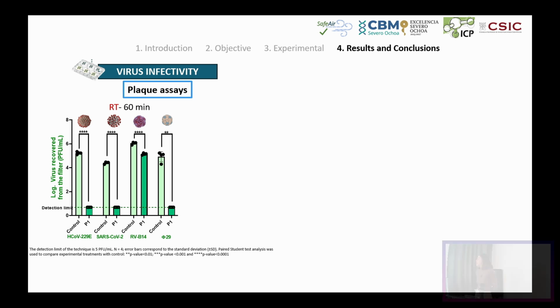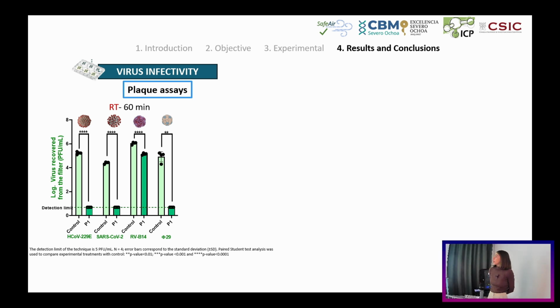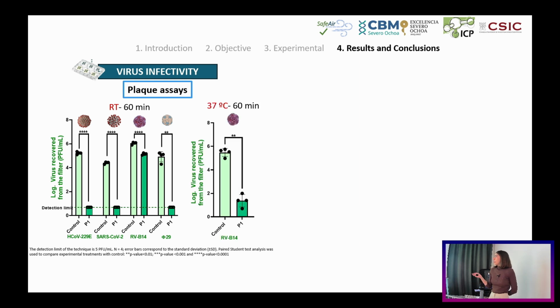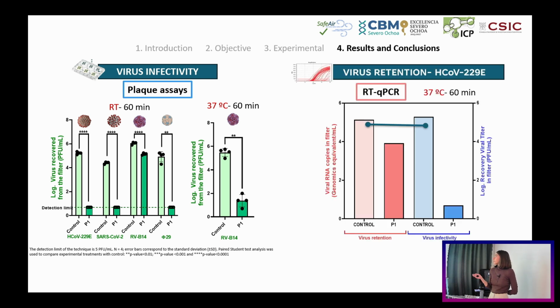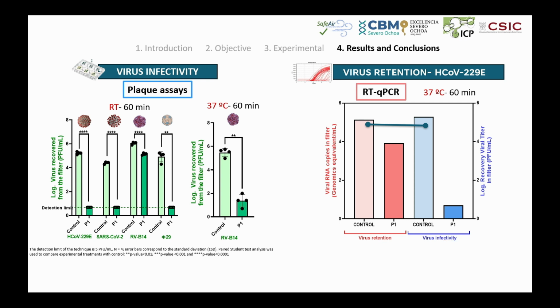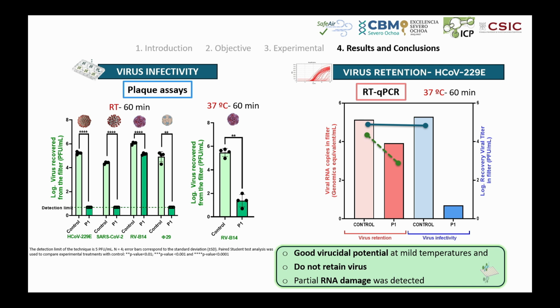Regarding virus infectivity, we can observe that at room temperature we obtain values below the detection limit except for the rhinovirus, but if we increase slightly the temperature until 37 degrees, we obtain greater results. To study the virus retention, if we observe this graph, we can see that the viral RNA copies are equivalent to the recovery viral titers, so there was no retention in the filter. However, the slight difference between the control, that is the filter without the active phase, and the filter with active phase means that there is a partial RNA damage.